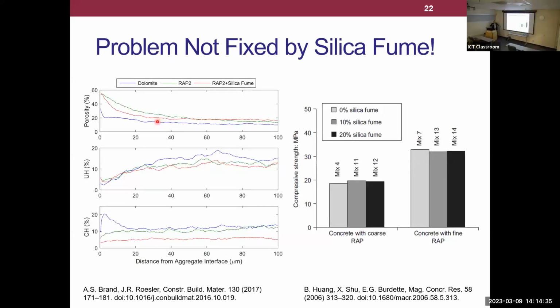Now typically, when we're designing Portland cement concrete, we add a whole bunch of stuff to it. One of the things we typically use to make high performance concrete is to add something known as silica fume. That's a supplementary cementitious material, and we tend to get a much higher strength concrete, much more durable concrete. But what we found, and what other studies have found, is that adding silica fume to concrete with RAP did not make an improvement. So you were basically wasting money by using silica fume here. Silica fume is about 10 times more expensive than cement, so you're literally throwing money away, right? We still see a little bit of an improvement in porosity here, okay? But it's still a fairly large porous ITZ. So silica fume doesn't fix our problem.